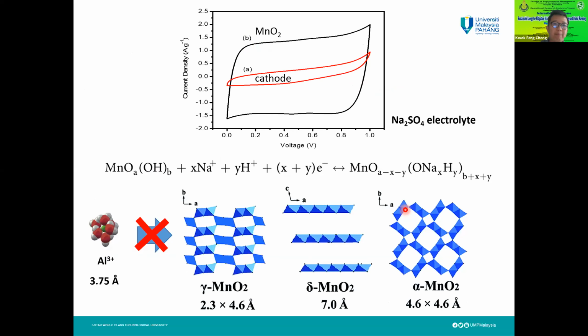We compare in terms of the charge storage. If you look at this cyclic voltammogram, very briefly, the explanation is: the larger the area under the curve, the higher the charge that it can store. So the spent cathode material actually cannot store a lot of charge anymore. For the manganese oxide, after we reactivate it, you can see that it increases substantially, roughly about 5-fold after we do the activation. But all this has been done in the sodium sulfate electrolyte. It's a very common electrolyte, and we can derive the equation for this charge storage, with the sodium ion being absorbed on this manganese oxide surface.